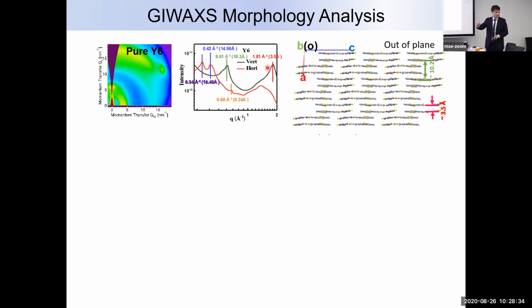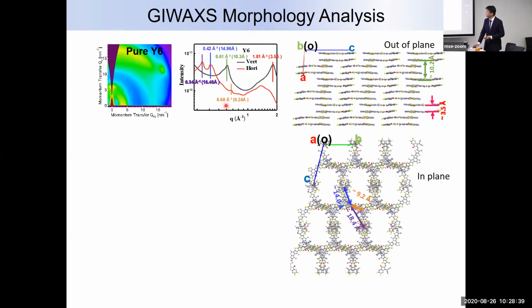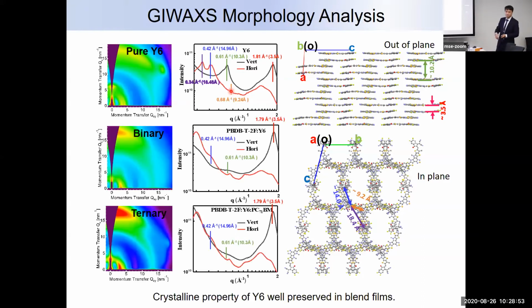This is good for electron transport. Okay, and we can also correlate the different lattice distances with the in-plane structure, which further proves that they have a face-on structure. And we also work with the binary, where we blend with the polymer, or even ternary, where we add some fullerene into the bulk heterojunction. We can see that this crystal structure is actually quite well preserved, even in the blend film.